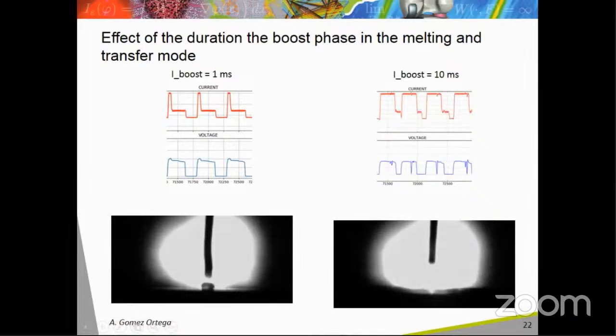One can see the droplets formed at the wire tip are too big to remain attached on the wire tip and are sprayed on the surface, producing sputters. So the increase of the pulse duration increases the melting rate of the wire, but it also promotes the formation of sputters. The limit values have to be identified, depending also on other parameters, such as the current value of the boost phase.